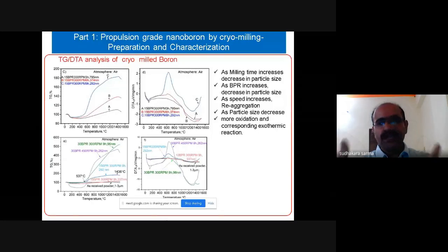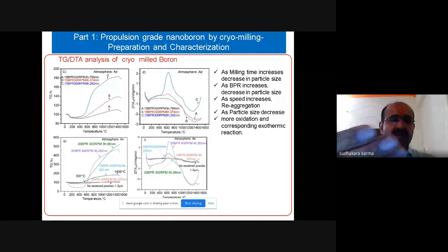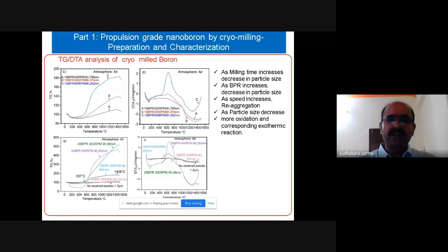The reason is the finer the particle size, the better the oxidation with the temperature. Better oxidation, so more mass gain. Oxidation means mass gain. We can also see the corresponding DTA curve. In the DTA curve, if there is a mass gain, oxidation is happening, so there will be exothermic peaks. We can see the exothermic peaks for A, B, C, that is 3 hours, 6 hours, and 9 hours of milling.